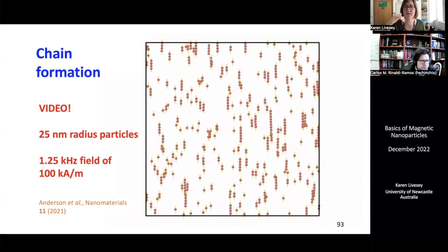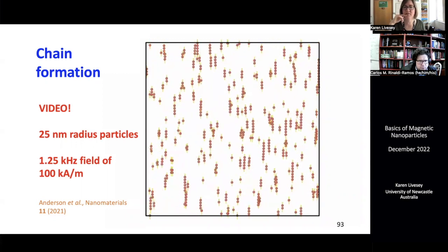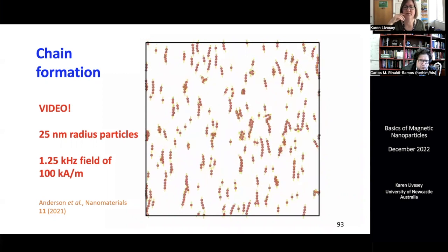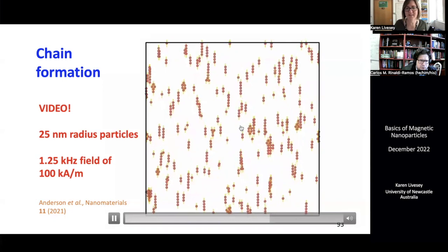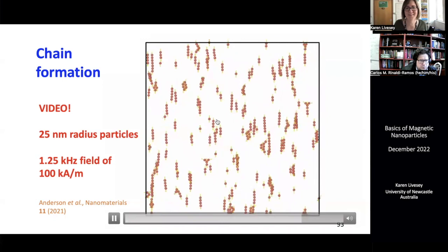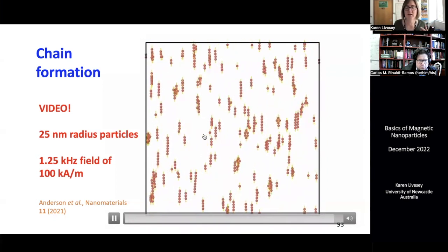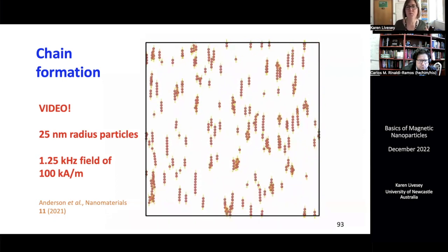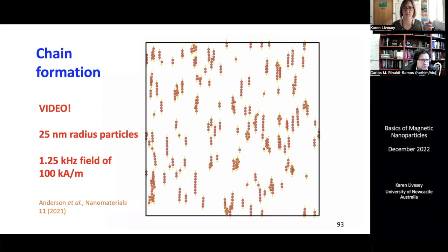So they're following the field, but at the same time, you can see that they're moving closer together because of those dipolar forces. So we get chains formed. We get some sort of more odd looking chains. This one here, for example, is like a fatter chain. It's 2 particles long. A lot of them are single particle chains, which happens when we've got a large field. If we have a weaker field, they can be kind of more messy, less ordered. So we see that chaining occurring, which is a combination of there being an external field and them interacting with each other.